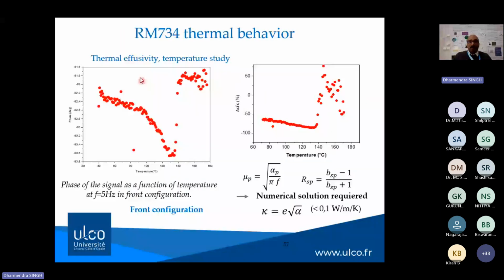This is the thermal effusivity with the temperature study. Here you could see that in the nematic phase the signal is high, and when it comes to the ferroelectric nematic phase it is less. To calculate this, a numerical solution is required, and we do a lot of mathematical treatment for that. And then what we found is that the thermal conductivity of this compound is very low. However, it is electrically conducting.